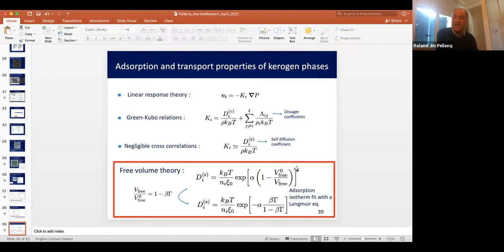But as I said, we are in a pore one molecule at a time, basically. So that second term is actually 0. So basically the permeance, this K, equals the transport coefficient divided by rho kT. Fine, super good. And not only that, we can show that the transport coefficient, this out of equilibrium thing, is actually equal to the self-diffusion coefficient. And that's a very key step, because of this one molecule at a time idea, the self-diffusion equals the transport property, meaning that the self-diffusion coefficient is actually an equilibrium quantity.